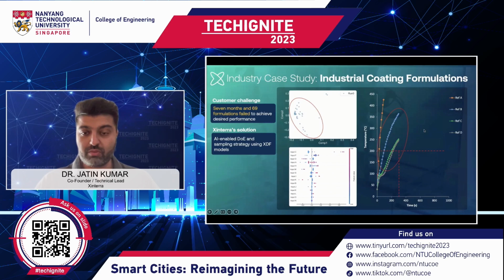So on the right, you see 3 of the best performers and bare metal. Bare metal, the one in yellow, reference A. And you can see that shoots up really, really quickly. But even the ones that are coated, they also shoot up and go well beyond 200 degrees Celsius in less than 5 minutes.